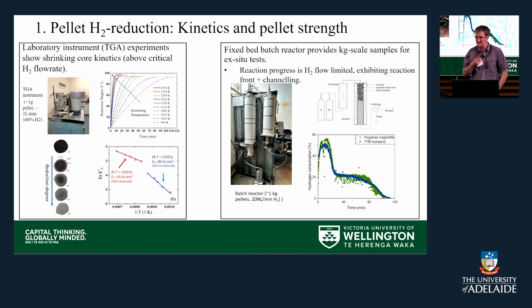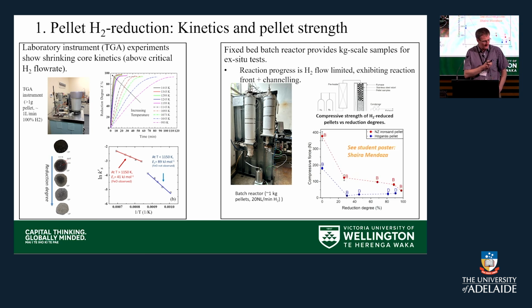What's interesting, of course, is the moment we move to a larger reactor to make material that we can test for other purposes, we then start to move into fixed bed reactor dynamics, and so what we actually see is a reaction front and often channeling between the pellets. That's a function of being at this intermediate scale, which is not a proper reactor and not a single experiment, not a single pellet either. But that does allow us to make enough material to do other tests.